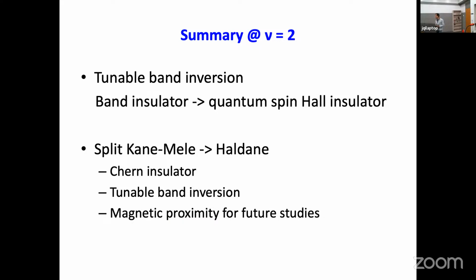Is it possible to gap the quantum spin Hall insulator edge with a magnetic field yet in this material? Actually, it's interesting that if you apply an in-plane magnetic field, you kill the edge state because the spins are Ising-like spins. So the spins are quantized in the out-of-plane direction. You apply an in-plane magnetic field, you introduce this spin mixing between the two channels, then you kill the helical edge state. But when you apply an out-of-plane magnetic field, it doesn't do much.